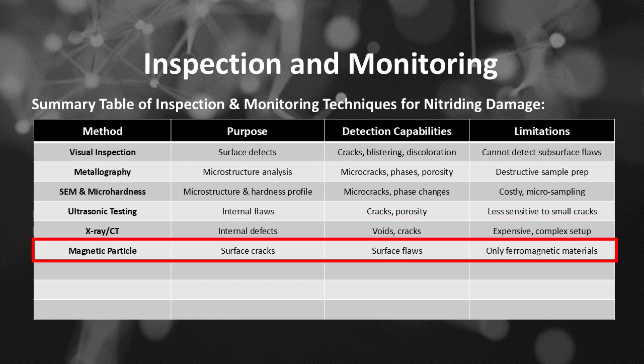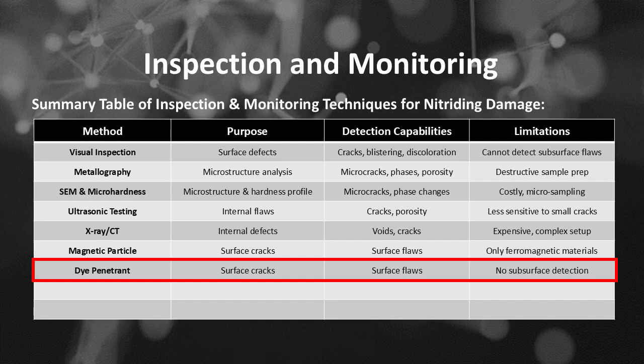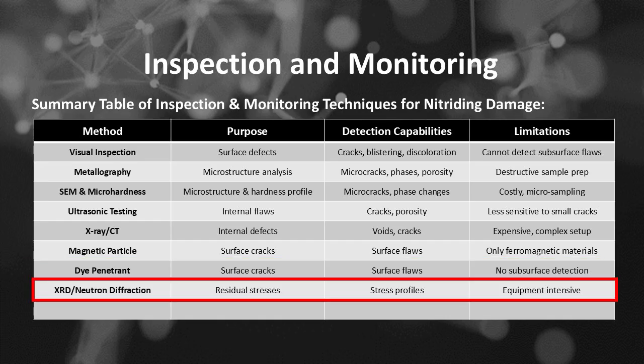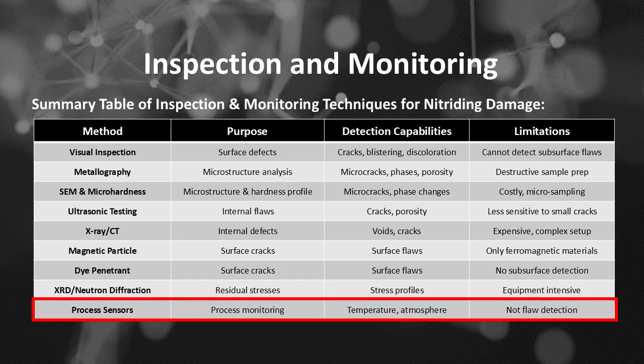If the method in use is magnetic particle, its purpose is surface cracks, its capability is to detect surface flaws, and the limitation is that it works only on ferromagnetic materials. If the method is dye penetrant, its purpose is surface cracks, its capability is to detect surface flaws, and the limitation is no subsurface detection. If the method is XRD and neutron diffraction, its purpose is residual stresses, its capability is to detect stress profiles, and the limitation is that it is equipment intensive. If the method is process sensors, its purpose is process monitoring, its capability is to detect temperature and atmosphere, and the limitation is that it is not flaw detection.